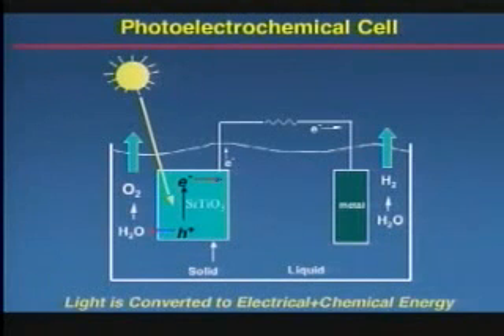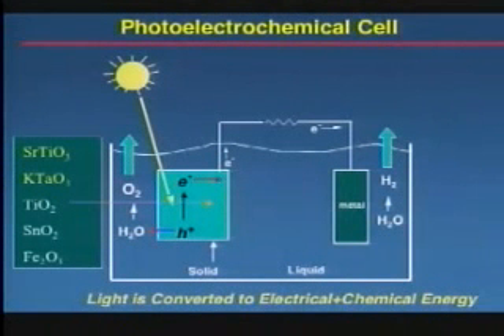We know this works. There are a series of materials that are stable in water and sustain the electrolysis of water with 1 to 2% efficiency, total solar. And the reason they're 1 to 2% efficient is because their band gap's wrong. So they work great on the moon because they only respond in the ultraviolet. Their band gap's about 3.2 eV. And the single band gap materials that work all fall into the metal oxide classes. There's a good reason for that: historically, in the 70s, these were the minerals that people used. TiO2 actually doesn't work unassisted, for the aficionados. You need about 1/10 of a volt in. This is worth 1.23 volts of electrolysis. So it's photo-assisted, but these other materials, especially strontium titanate and potassium tantalate, are unassisted.